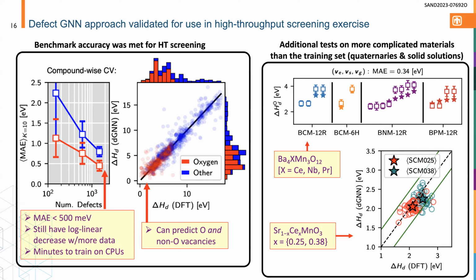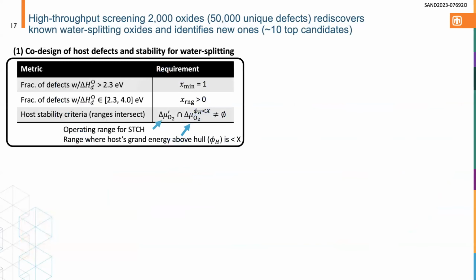And then on the bottom is a different class of material called a solid solution, where basically you have disordered cation sites. This is the SCM material, which is known for its water splitting capabilities, and just confirming that the GNN, even when the range of enthalpies is pretty close, can still correlate within that particular structure. And most importantly, it captures the fact that the vacancy formation energy increases as you increase the cerium content in these solid solutions. So that gave us the confidence that we could go ahead and start screening new materials.